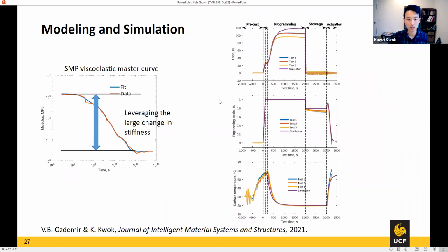And so this is a page where we summarize all the results. On the left-hand side is the viscoelastic master curve that we obtain separately from relaxation creep experiments. And you can see that the modulus changes quite drastically over time. But that drastic drop can be shortened or lengthened by the temperature of the material. So what we are trying to leverage here is this large change in stiffness that can be modulated by temperature. This master curve can be shifted to the left and to the right by increasing or decreasing the temperature.